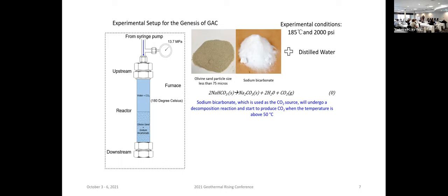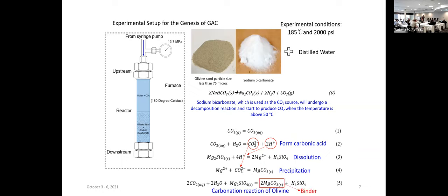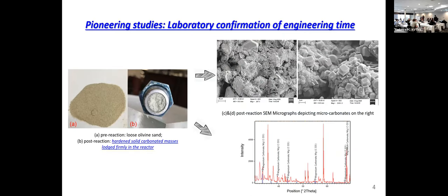When temperature goes above 50°C, sodium bicarbonate undergoes decomposition, producing CO2. The CO2 gas dissolves in water to form carbonic acid, which reacts with magnesium silicate in a dissolution reaction to release magnesium ions. Those magnesium ions then react with carbonates. If you add up equations one through four, you get the final carbonation reaction of olivine — equation five — where magnesium carbonates act as the binder. I know you hate equations, but I just want to show how simple the reaction is.